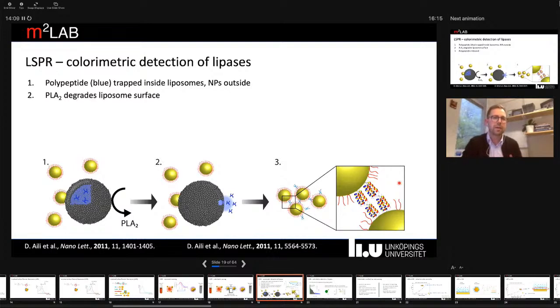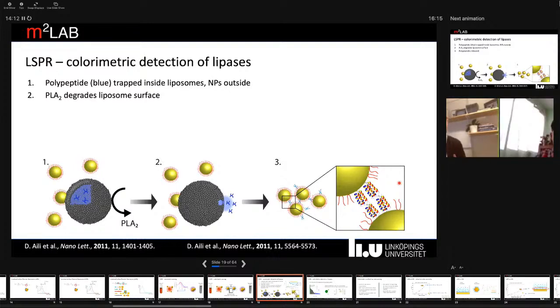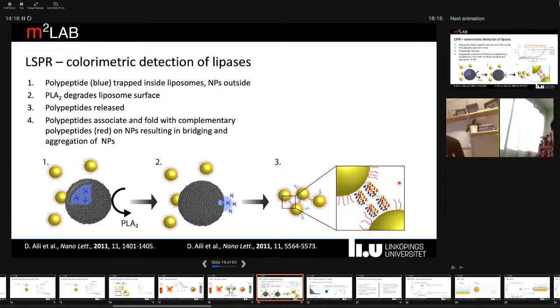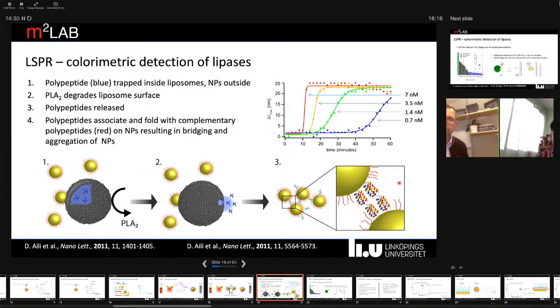Then when we add phospholipases, they start to degrade the lipid bilayer. Eventually the peptides will be released due to this degradation process, and this triggers an aggregation of these particles. We can monitor this as a redshift of the plasmon band, which is shown here on this axis, and we monitor this process over time. We can see that we get a slightly different magnitude of shift depending on concentration, but above all, the higher the concentration or activity of this enzyme, the faster is this release.